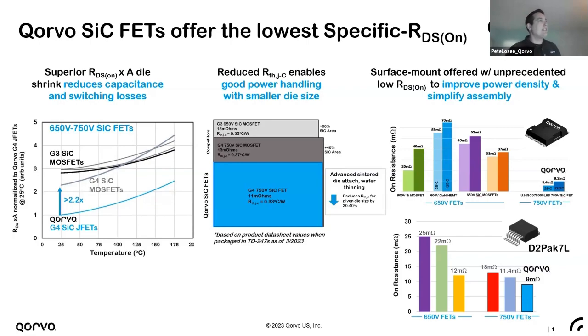So, lower RDSA means that you shrink the die and you get advantages like lower capacitance and lower switching losses associated with that. Obviously, you get better utilization of the substrate and presumably a better price point. But again, doing that without improving thermal resistance will start to limit your thermal or power handling capability. And so what we have to do in silicon carbide, as die shrink happens, is keep beating down this thermal resistance.